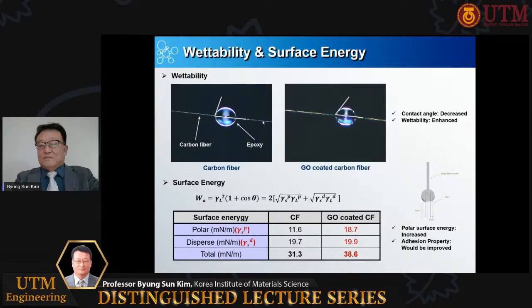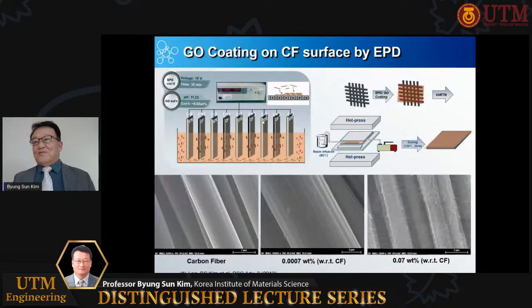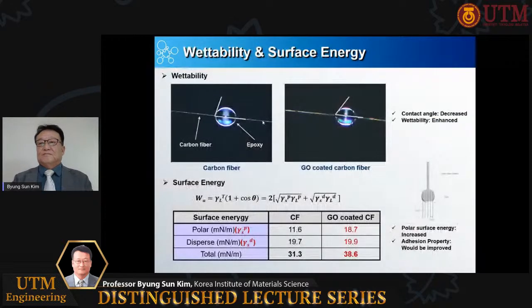As shown in the same morphologies, graphene oxide is very well coated on the carbon fiber surface with 7/10,000 and 7/100th of a weight % of graphene oxide, respectively. Here, the interfacial property of graphene oxide coated carbon fiber is investigated in terms of both quantitative and qualitative approaches. When a micro drop of epoxy resin is on a single carbon fiber, graphene oxide coated carbon fiber showed less contact angle, which means the graphene oxide increased the wettability with epoxy resin.